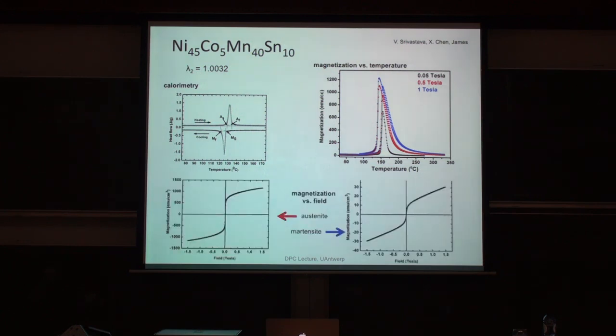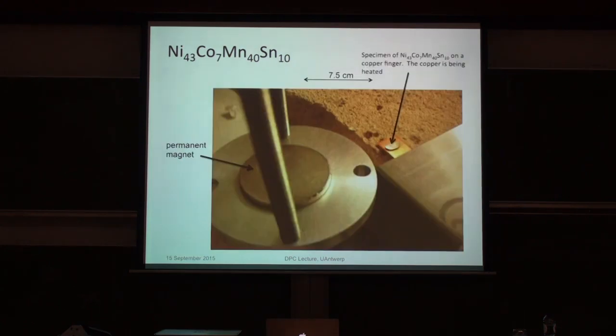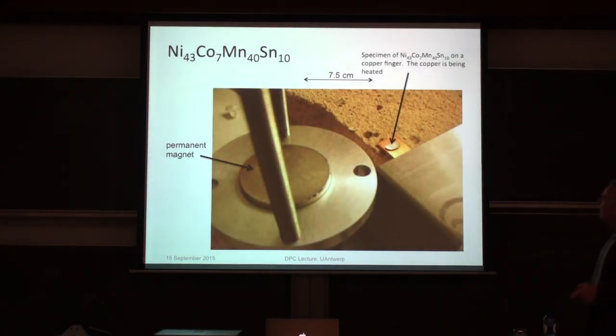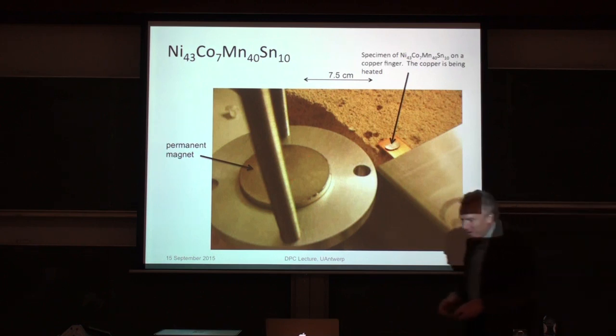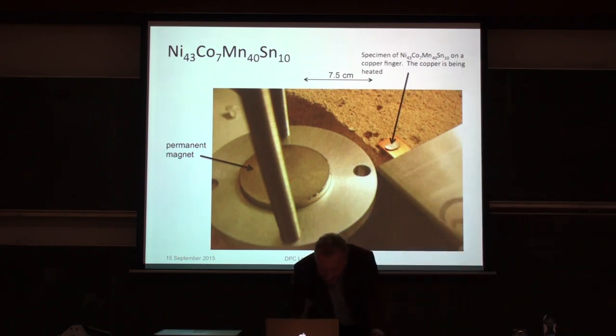And it has very interesting magnetic behavior that I won't go into, but there's a tiny bit of ferromagnetism in the martensite, but it's actually anti-ferromagnetic, and I won't go into those details. But the fun thing is they took a piece of that material and they stuck it on a copper finger, and they heated the finger. And then they happened to put a permanent magnet 8 centimeters away or so, and this is what they saw.